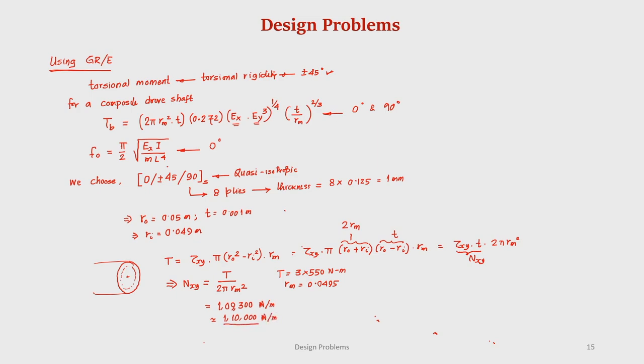So, the problem is now we have a laminate, which is subjected to only, what is this laminate? 0, plus minus 45, 90 graphite epoxy, which is subjected to only N x y. Okay, all other N x, N y, M x, M y, M x y is equal to 0.